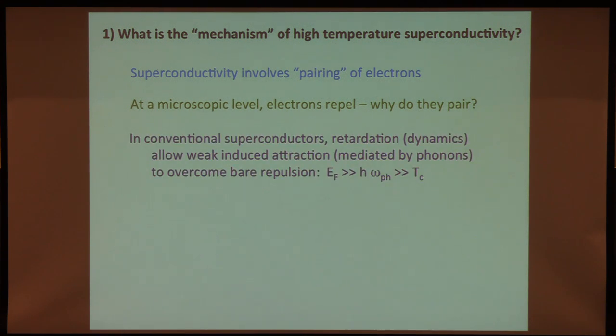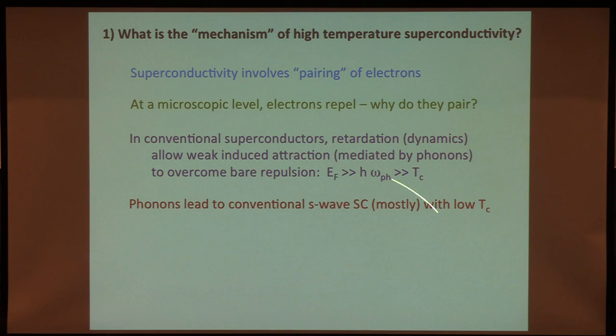And in the conventional superconductors, we understand the basic principle that's involved. It comes from the retardation of the phonon dynamics: even though the induced attractive interaction is probably weaker than the bare repulsive interaction, because the induced attraction is retarded, it can overcome the stronger bare repulsive interaction. And as long as this hierarchy of scales holds, that the Fermi energy is large compared to the phonon frequencies, which are in turn large compared to Tc, we have a moderately well-controlled theoretical understanding of how conventional superconductivity arises. Because we're dealing with an induced attraction, and because the induced attraction is generally fairly local in real space, conventional superconductors are mostly simple S-wave in their character.